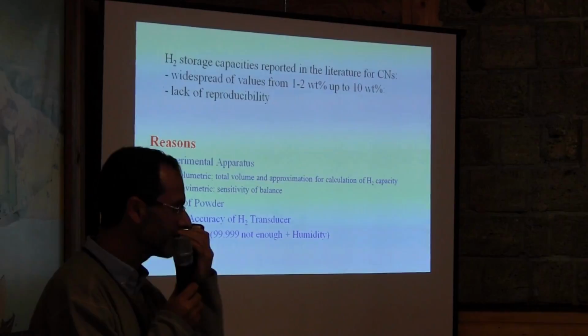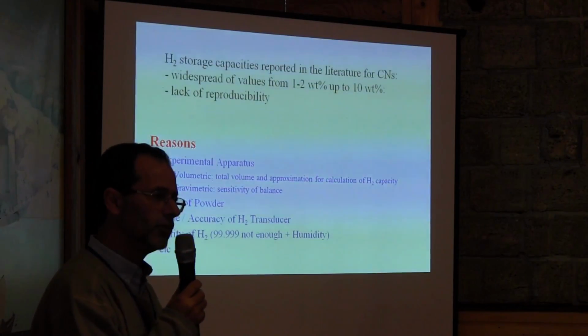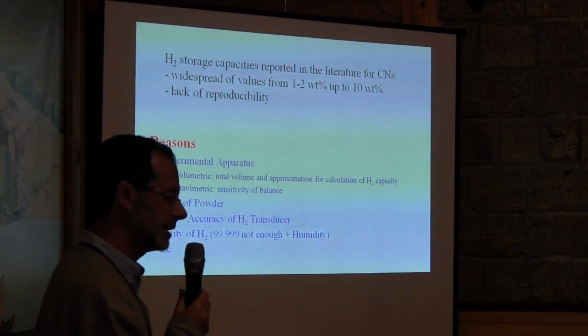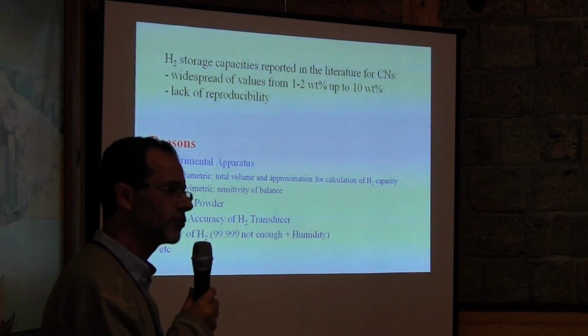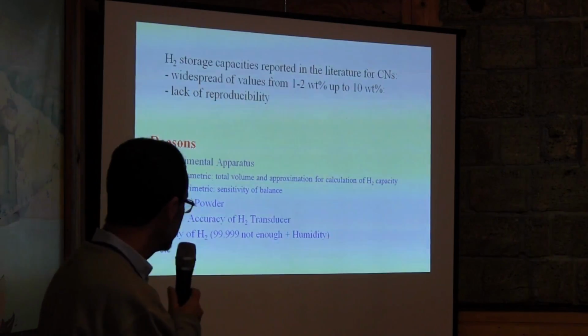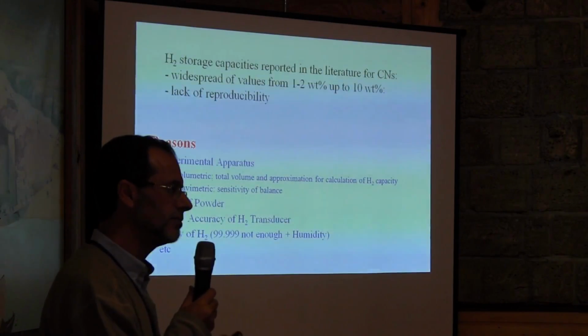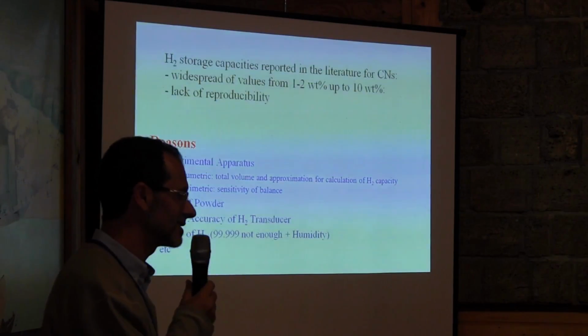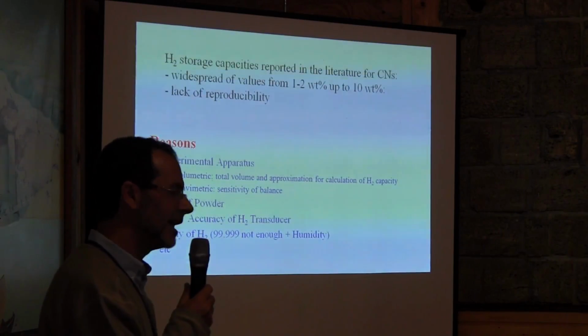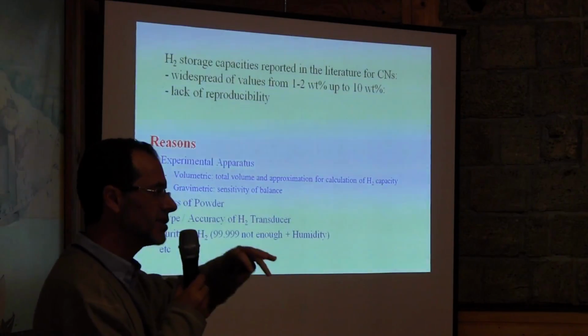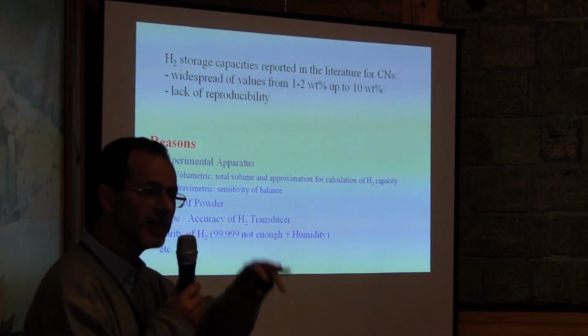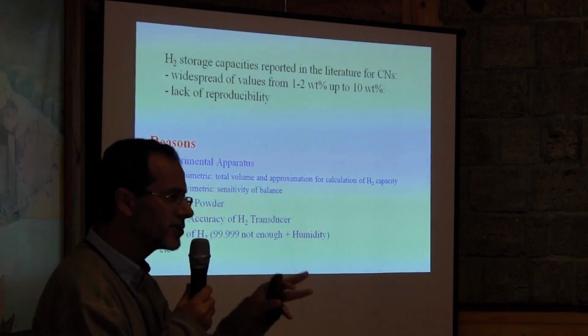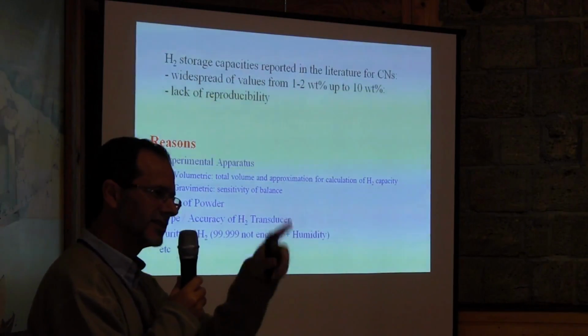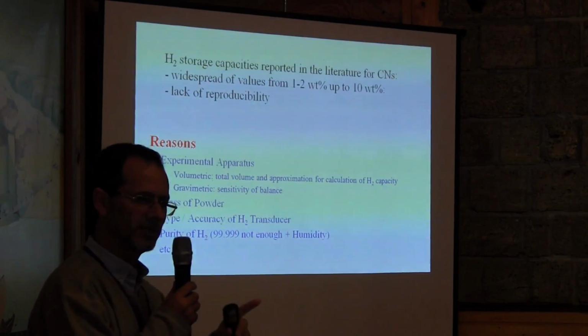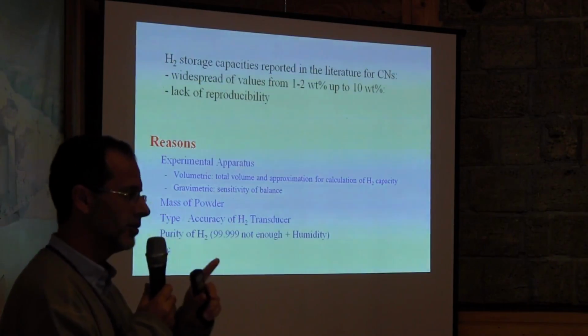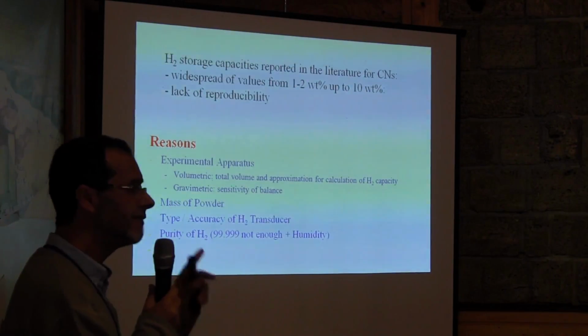Why? Then what we did, to be sure, we use what we call, I will show in the system later, liquid nitrogen trap. When you say the purity of hydrogen, 99, what does it mean 1%? Do you know what is 1%? It's humidity. And the humidity can be physisorbed on carbon nanofibers. It's very active. So it will be physisorbed. So what you measure, it's not hydrogen capacity or hydrogen adsorbed. It's finally humidity. It's adsorbed, even 5N.